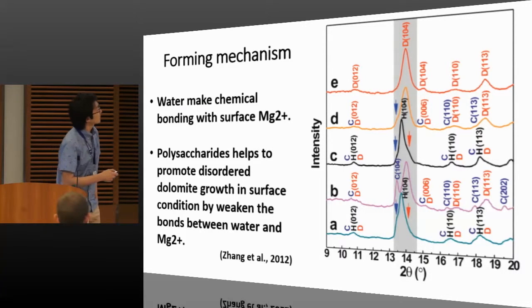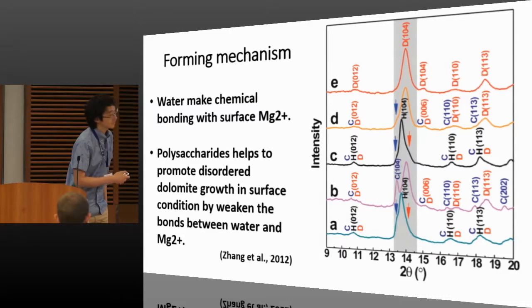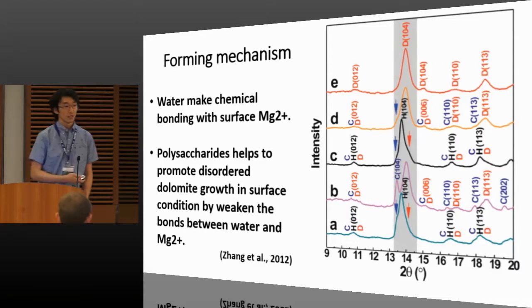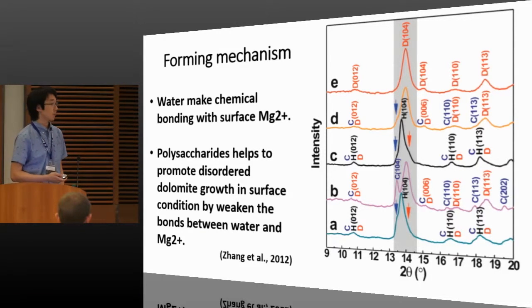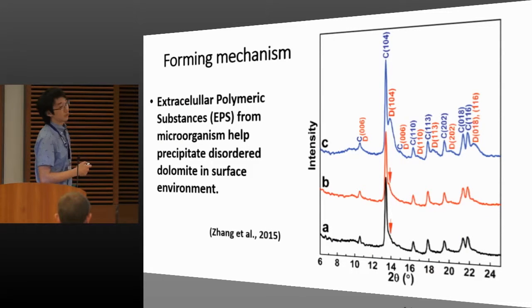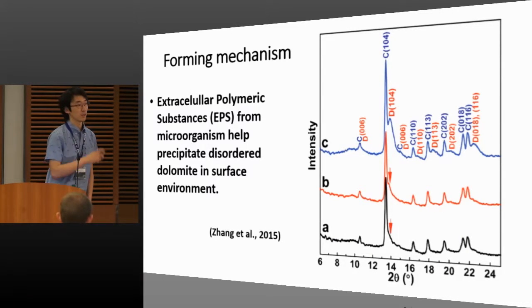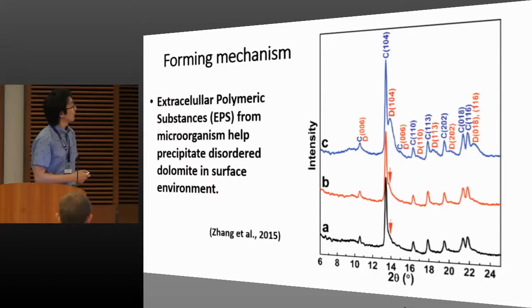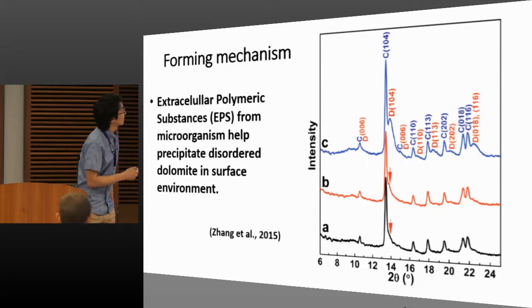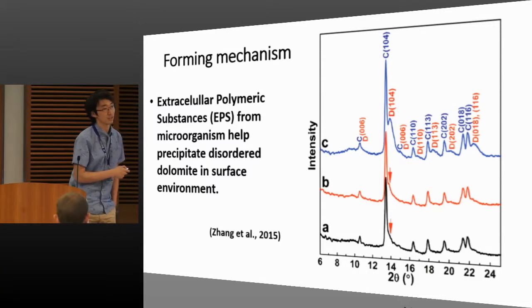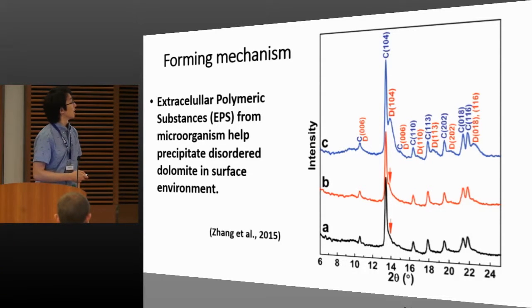And then they successfully synthesized dolomite, disordered dolomite. You can see in the XRD data here, that's really weak. And so polysaccharide works. What else? What's the next step then? So they use EPS. Polysaccharide is a major component of the EPS, and they also successfully synthesized dolomite by adding EPS to the solution in a reasonably short time.